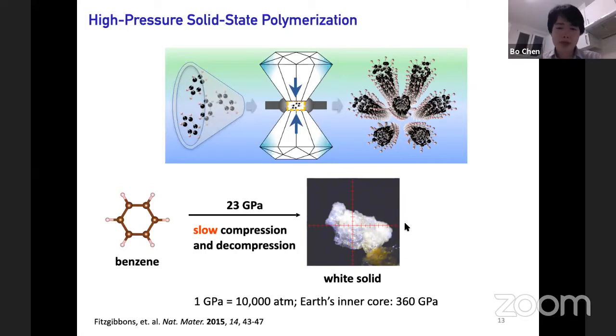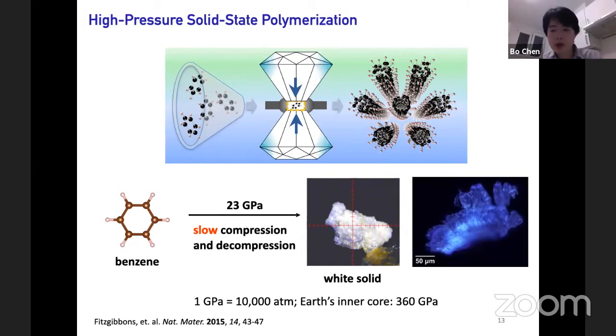And immediately from the color, you can tell that this material is insulating. And this is actually, I would say, a very remarkable transformation because it is the first time in 100 years of history of people compressing benzene that an ordered product is formed and recovered. The order can be seen from this image, this optical image.